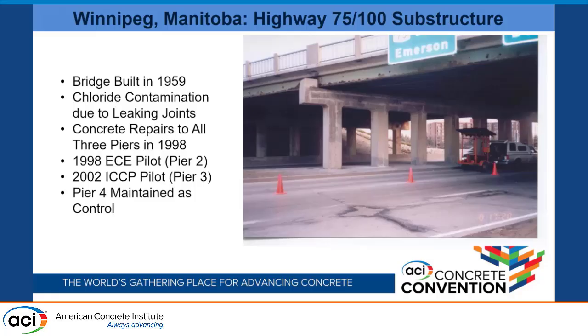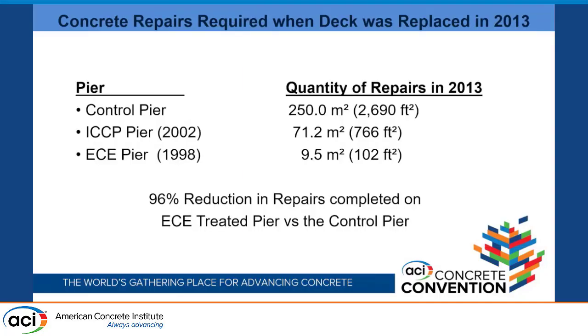And finally, another project that was done around the same time, a couple of years later. This is a bridge in Winnipeg. It's actually not far from where I live. And this bridge was built basically in 1959. They did rehab to it in 1998. And at the time they did the rehab, they did chloride extraction on one of the piers. A few years later, we did impressed current cathodic protection installation on another pier, and one pier was maintained as a control.